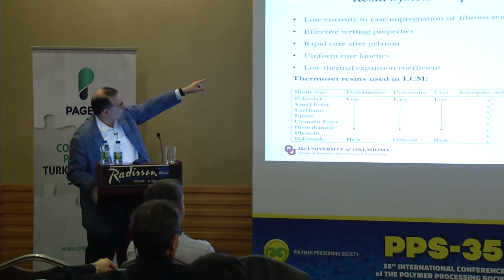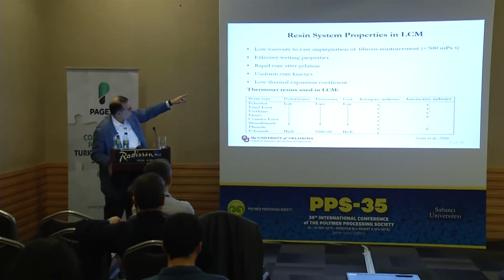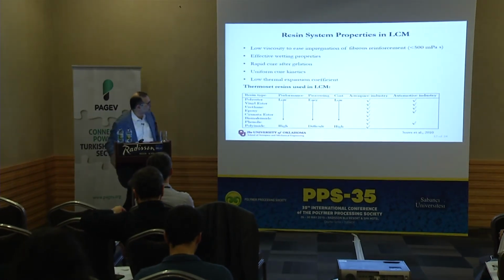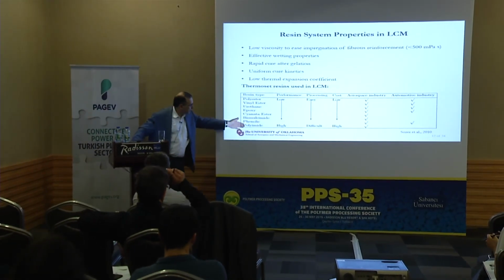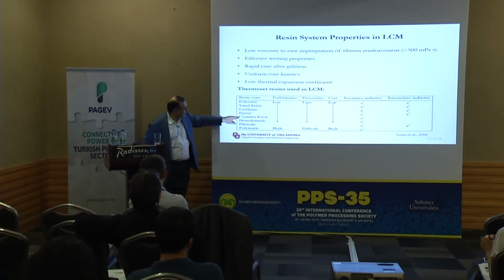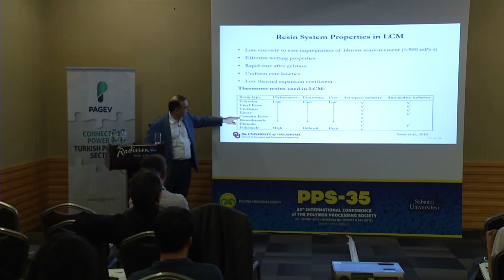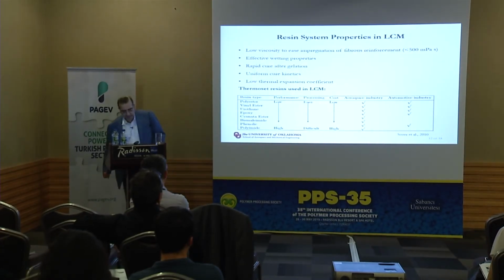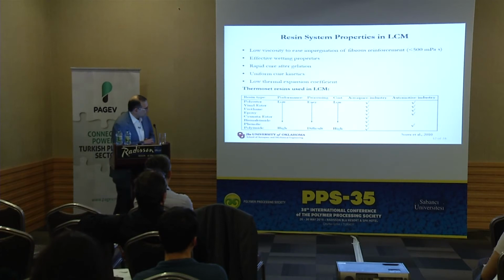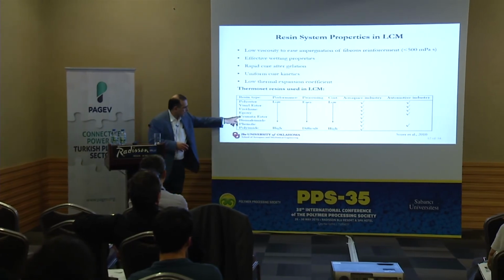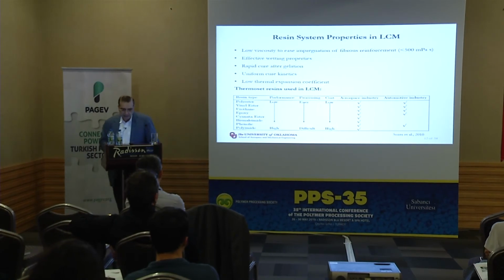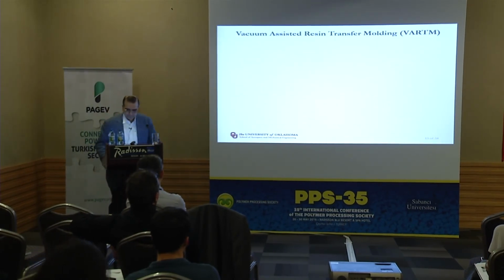All right, so I am here saying that the resin is very important, has to be less than 500 centipoise, less than glycerin. We talked about that. You have to choose the wetting properties, the cure kinetics. You need to also look at the thermal expansion coefficient. There are some candidates, cyanate ester and bismaleimide. These are really nice, and they are used in certain high performance applications, missiles and rockets and things like that. Bismaleimide, BMI, for high temperature applications.